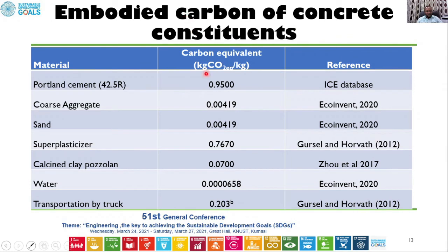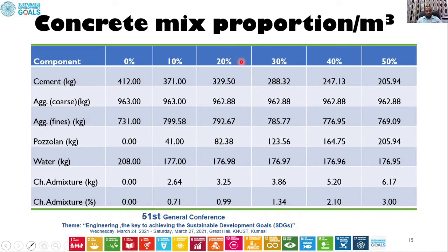So this table is showing the embodied carbon of concrete constituents. Here we have Portland cement, which was picked from the ICE database, which is 0.9500, and then we have sand, we have the admixture, the water, everything is here. So these are the results. This is the concrete mix proportion per meter cube. Here you see the various mixes which are labeled as 0%, 10%, 20%, up to 50%. The cement content used and the Pozzolan content are here, everything used in the concrete mix is tabled here.